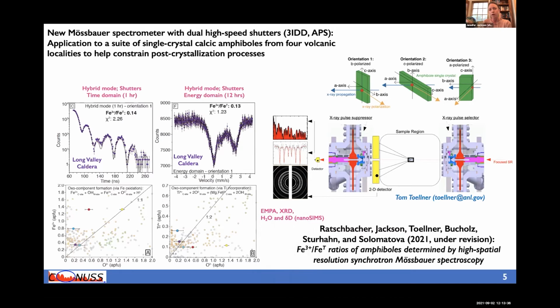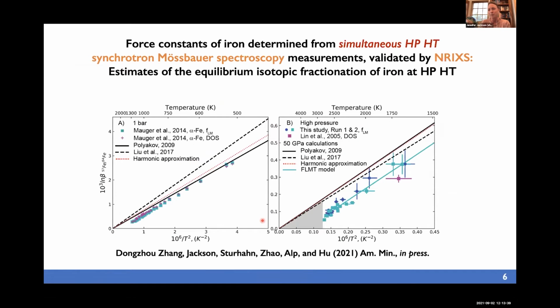And so finally, before we go down to the core mantle boundary, one thing that we've been able to do is utilize synchrotron Mössbauer spectroscopy to go beyond determining valence and spin states to actually extract the force constants of iron at simultaneous high pressure and high temperature conditions. And this is work led by Dongzhou Zhang. It's also been validated by high pressure, high temperature NRIXS measurements, and also measurements using NRIXS at room pressure.